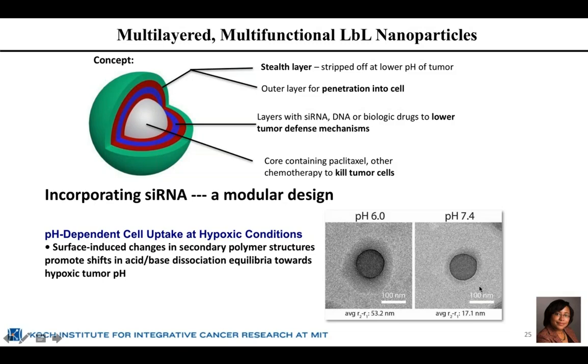And we have these fairly well arranged nano layers, as you can see on the image on the far right. What we have found is that when we use layer by layer films, we can use the unique capability of combining acidic and basic groups to generate nanoparticles that have an isoelectric point, that these nanoparticles can actually shift in charge as we begin to protonate the carboxylic acid groups that may be in the outer layer. And that allows us to essentially lose some of that negative charge. It also erases some of the ionic crosslinks and the film swells.